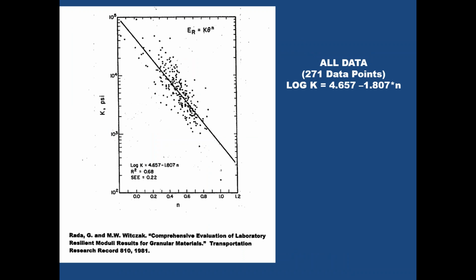Back many years ago, Gonzalo Rada, who was one of Matt Witczak's students at the time, did an evaluation of all the data they could find. A lot of my numbers are in there as well from our early work on modulus testing of granular material, and they developed a relationship between K and n as shown here, okay? So if you have an idea of where you are and you do a test and get something plotting down here, you may find that you've got a bug in your testing approach and your data. If you're not following somewhere along that line close by, you're probably not doing it correctly. So we need to keep that in mind.